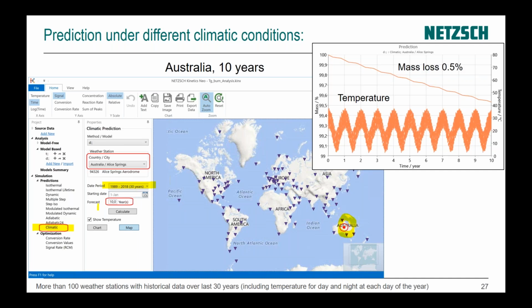Then we can make predictions for 10 years and see here we have temperature and how mass will be decreased during these predictions. Here we take into account only decomposition because of temperature. We do not take into account sunlight. So if your material is in the sunlight, then the light has also an additional effect and decomposition could be faster. But if it's without direct sunlight, then we have real predictions.